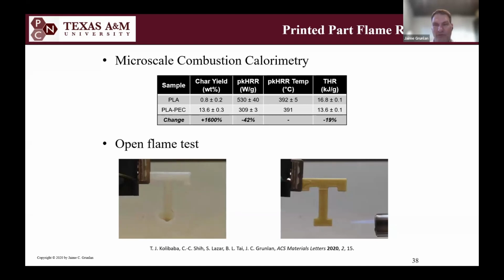And then when I torch the 25% PEC PLA, it just chars into a mess. It doesn't even truly ignite. You can see the moment the torch is taken off, there's no burning, and you can keep bringing the torch back in and burning, and you don't further damage the T, in that case, the printed part.